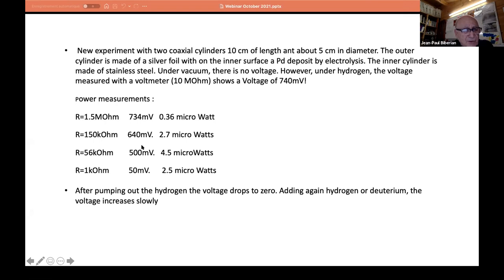Now we have 500 millivolts. You can almost light up an LED with that, almost. If I pump out the hydrogen, the voltage drops to zero, so you need the hydrogen. But when you add the hydrogen or deuterium again, the voltage increases slowly. It's very surprising. It seems that it takes time to load the layer of palladium so that the hydrogen will go inside. I didn't see a big difference between hydrogen and deuterium. It seems to be about the same.